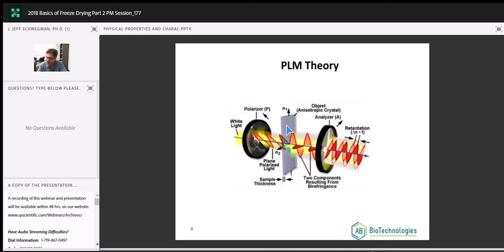It then passes through our sample. Now if our sample has anisotropic crystals, it breaks the waves into the perpendicular waves, the ordinary and extraordinary wave. We then pass it out through the analyzer, which is another polarizer. What that does is it takes pieces of both of those waves and we get essentially retardation in the wavelength. So this slows down or speeds up and we see that as changes in the wavelength or color, if you will.